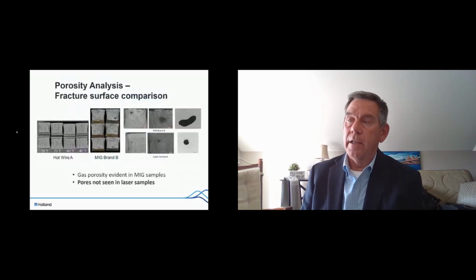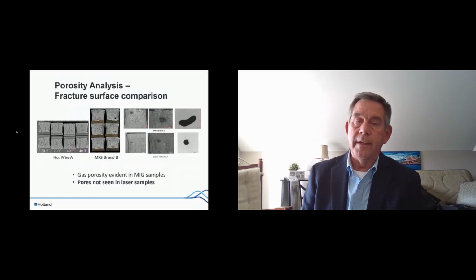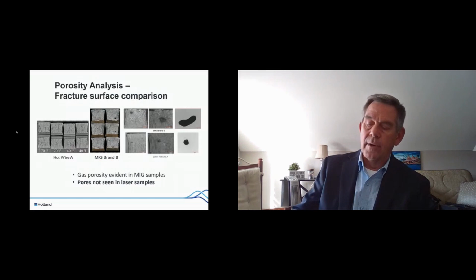Porosity is another challenge when MIG welding because of the arcing process, there tends to be gas pores in the material. As you can see in the center, with the MIG welding, the gas pores are very visible in a cross section from the impact test. Whereas with the laser process, on the far left, there's no visible sign of porosity. You have to magnify it a bit in order to find any porosity at all. So the pores are not seen in the laser samples, even though there are very small pores there. They're very large and obvious in the MIG welding process. So again, a much better interpass layer characteristic.